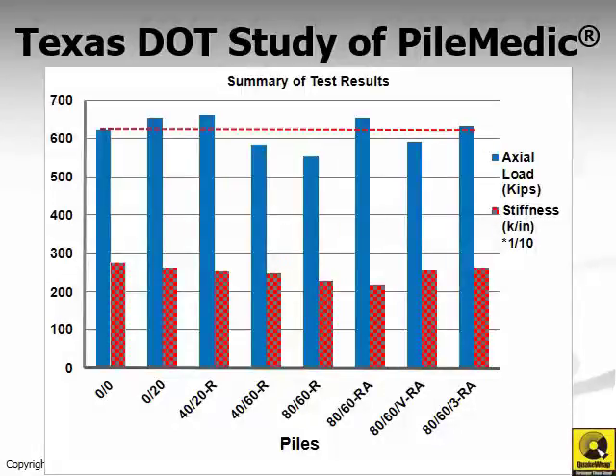So if we look at the number of specimens that have been tested, this is the summary of the results, and we are showing the axial load as well as the stiffness of each of these columns compared to the original one. The first column, 0, 0 on the left, is the original undamaged control specimen that was tested. The other columns shown as 0, 20 or 40, 20 and so on, the numbers indicate the percentage of thickness loss in flange and web respectively.